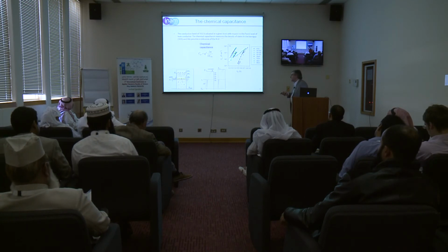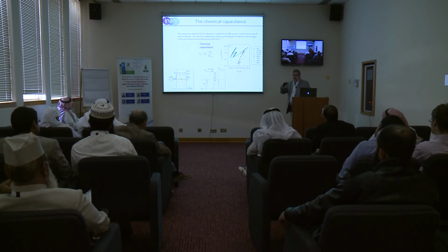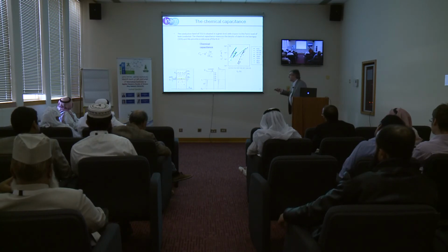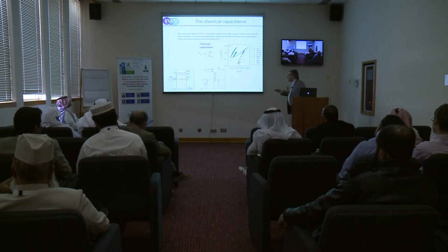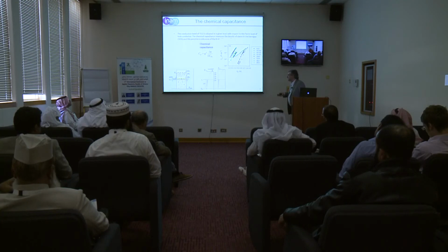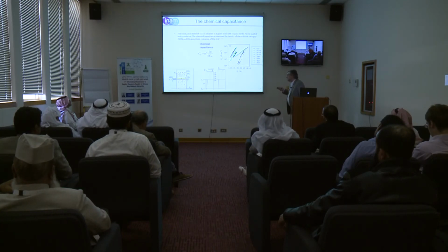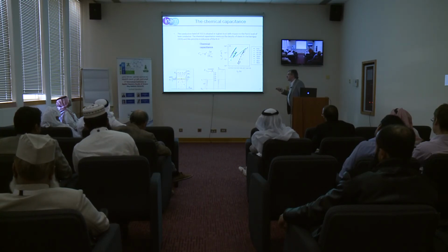And then what happens is that when you modulate the voltage in the solar cell, which is like the Fermi level here, you change the occupation of these states in the band gap. And in the end, with voltage, you can really scan the density of states. So this is the typical density of states of anatase titanium dioxide used in dye-sensitized solar cells and other applications.